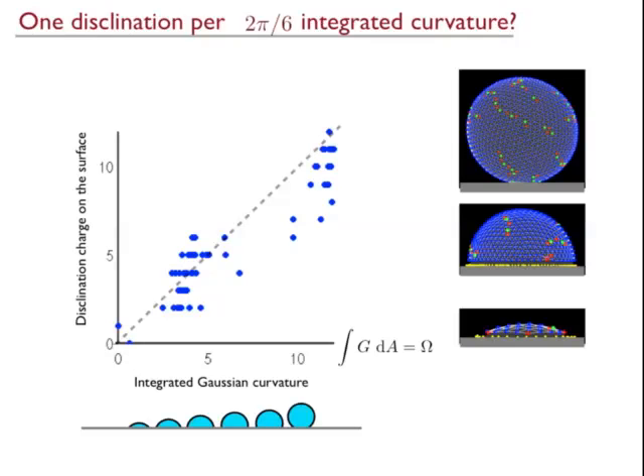And what you might expect, for example, is that when it's flat, there are none on the surface. When it's fully blown, there are 12 on the surface. That means there has to be -6 on the edge there, but that's okay. I'm only counting the ones on the surface. And you expect, for energetic reasons, that I'm just going to get a straight line here. And essentially what you find is you get something that looks pretty much like a straight line.